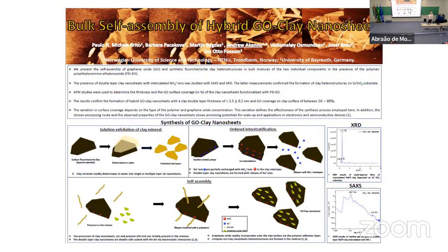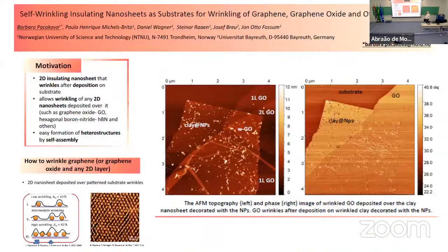Another poster we had is this. We make hybrid suspensions of clay and graphene oxide. I mentioned that clays are these 1 nanometer thin layers, but clays are non-conducting. So it's interesting for various applications to mix them with conducting layers and make hybrid structures of non-conducting and conducting. This is what we have done here. We have found a way to attach graphene oxide to the clay. So that was another poster.